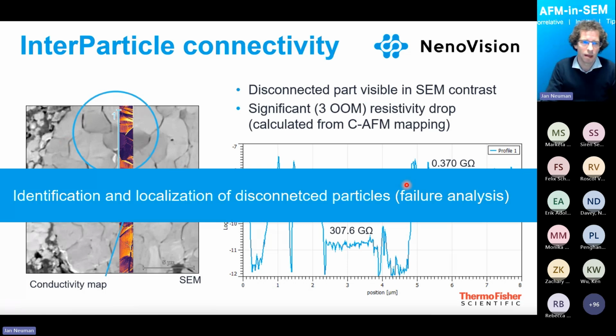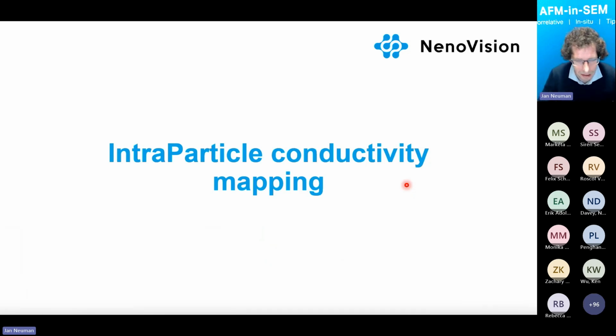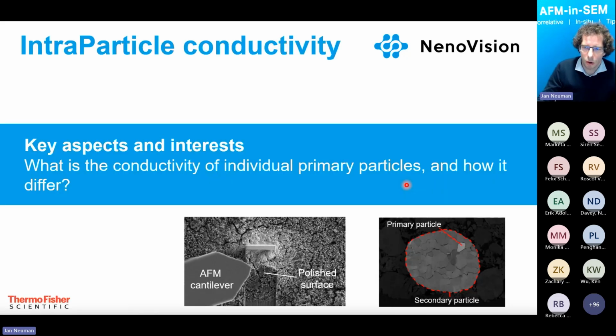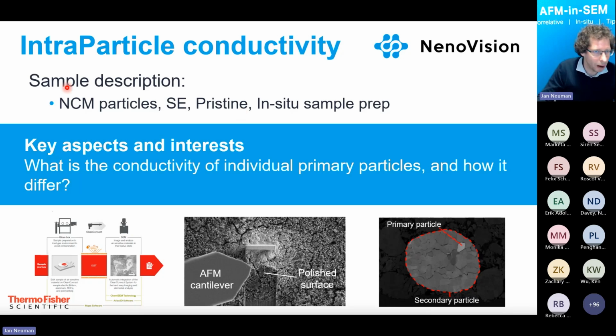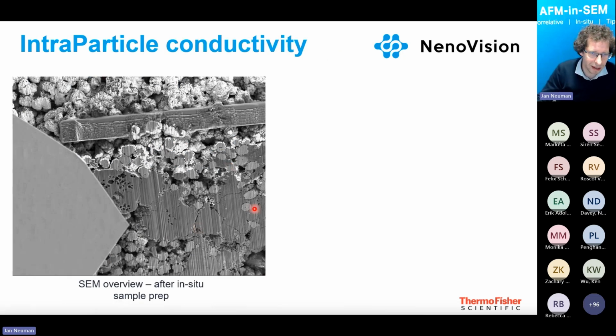So, failure analysis. The last example which I would like to show is intra-particle conductivity mapping. As I explained, we have a secondary particle, which is composed of small primary particles. And the question is, is the conductivity the same for all of them, or does it differ? For that, we use NCM particles again, with the solid electrolyte in the pristine stage. But in this case, I will show it on in situ sample preparation. Just to remind you, we use a focused ion beam to prepare the cross-section directly inside the SEM, and after that we directly measure.